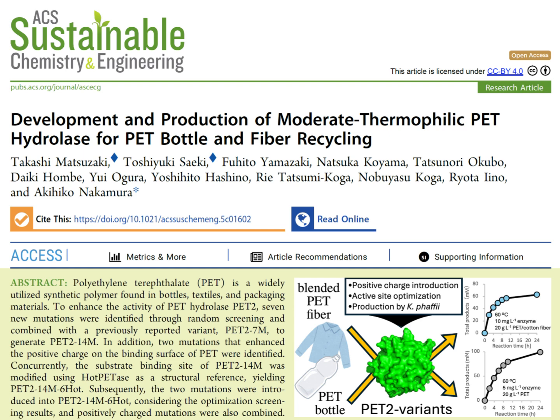Okay. At a typical setup, say 20 grams of PET per liter and 5 milligrams of enzyme per liter, PET2-14M completely degraded 95% of the PET within 24 hours. And that was at a moderate 60 degrees Celsius. 95% in 24 hours. How did LCC compare? LCC-ICCG actually achieved 91% degradation faster, in about 10 hours, but it needed that higher temperature of 72 degrees Celsius. So faster but hotter for LCC. PET2-14M is a bit slower but works at a lower temp.